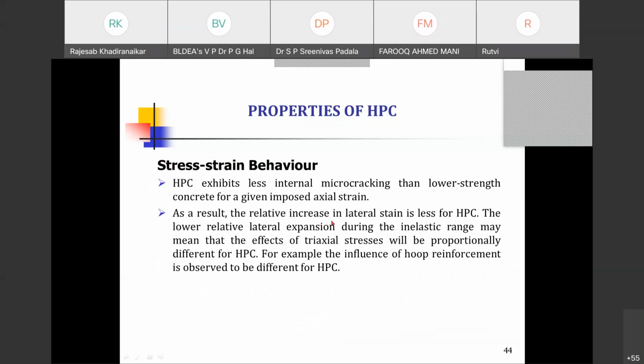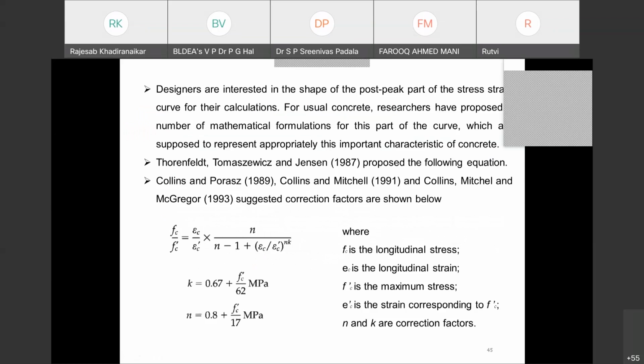As a result, the relative increase in the lateral strain is less for high performance concrete. Less micro cracking means naturally the lateral expansion is also less. The lower relative lateral expansion during the inelastic range may mean that the effects of triaxial stresses will be proportionately different for HPC compared to conventional concrete, and the influence of hoop reinforcement is observed to be different for the high performance concrete. And many people, of course, have proposed empirical equations for the stress strain characteristics of high performance concrete.